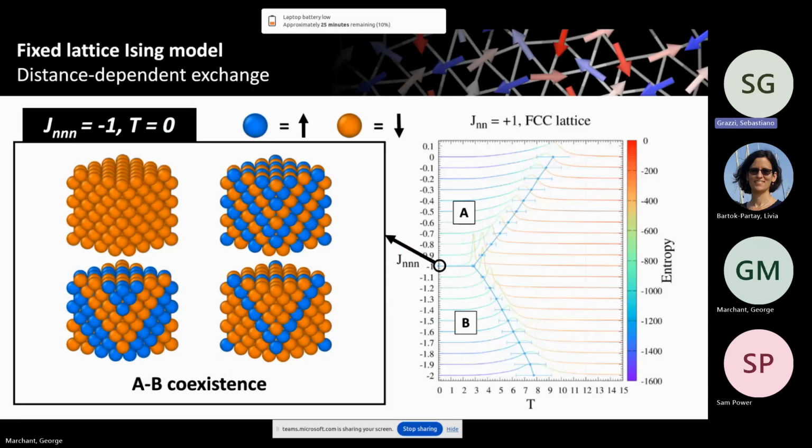And so nested sampling samples this coexistence between ferro and antiferromagnetism, where it samples a fully ferromagnetic state, it samples a fully antiferromagnetic state, but it also samples slightly more complicated structures where you have layers of up, down, down, and up, down, down, down. And it's possible to show analytically that these two structures should in fact be equal in energy.